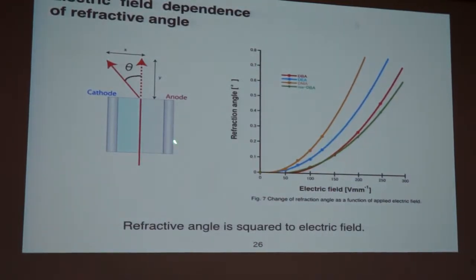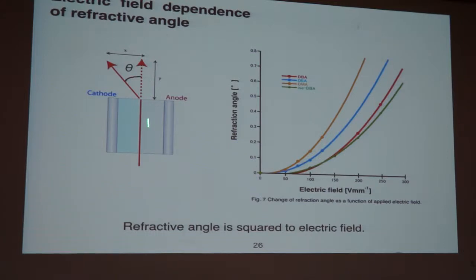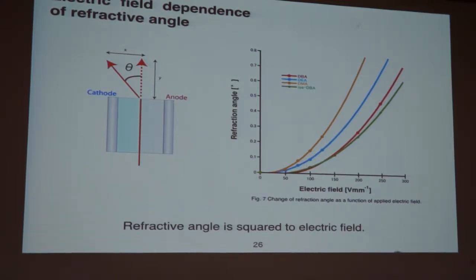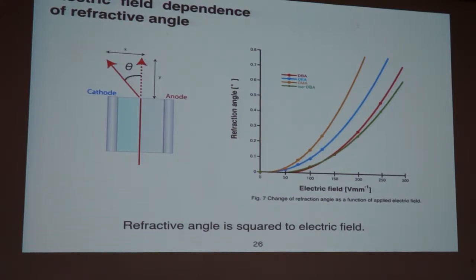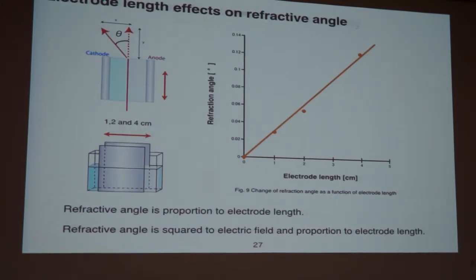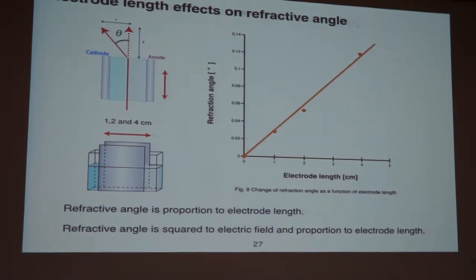This is the image. Actually, the laser beam doesn't go through straight. It's actually bent in the gel. But for simplicity, we measure it this way. And the result is like this. And as you see here, this is proportional to the square of the electric field. The Kerr effect is observed. When the length of the electrode is increased, then the refraction angle naturally increases proportionally. These are the phenomena that we observe.